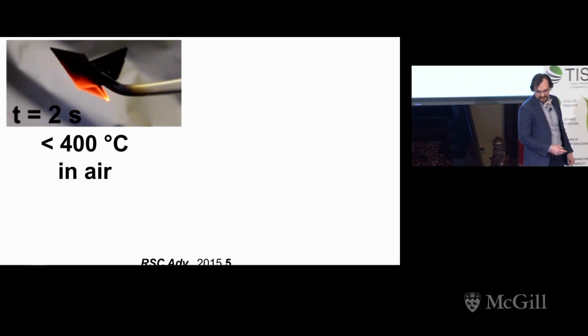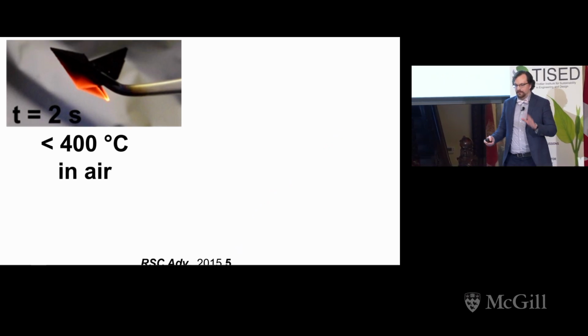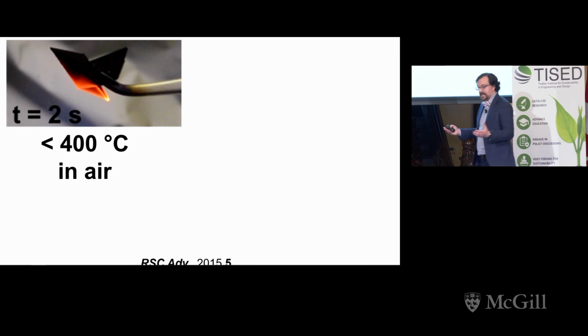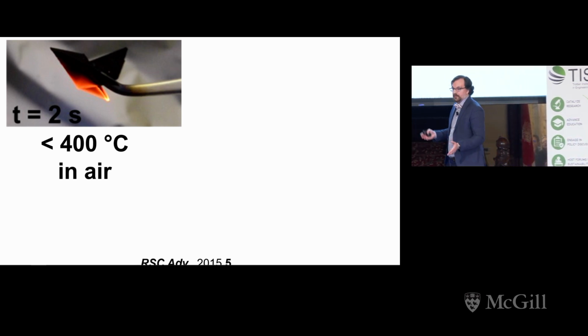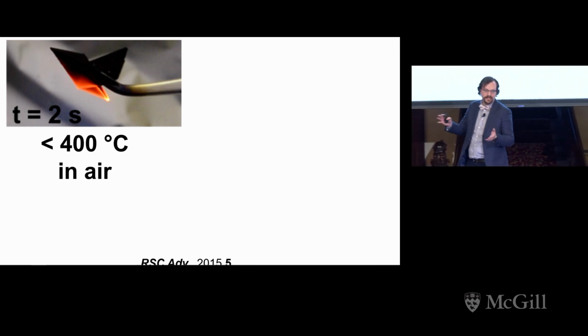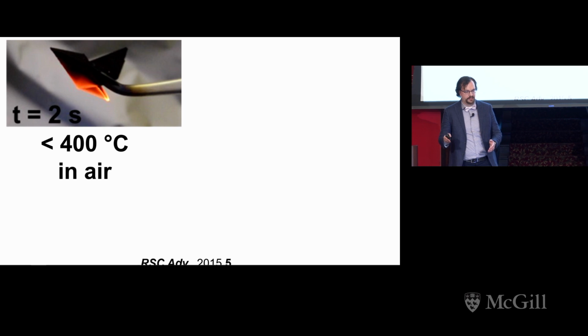Now, going back to the carbon nanotube. Carbon nanotubes are actually stable for CO2 methanation. Their temperature range usually caps out around 400 Celsius. But there's a slight problem.